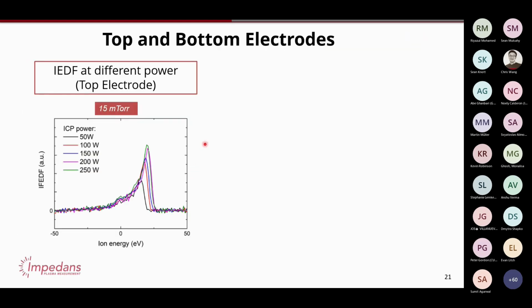Next, let's look at top and bottom electrodes. So what happens if you change the power on the top electrode? This is a case where it's an ICP system. So everything is kept constant except the power on the coil at the top is being increased. And it's kind of what you expect. The ion flux increases. So the number of ions that are available to do your processing increases. So this would increase your etch rate or increase your dep rate.